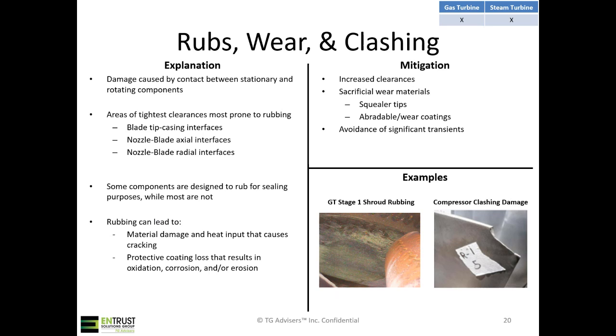The other thing that you can do is avoid significant transients. The big thing is that if your gas path is really hot, but your casing is still cold, you can cause severe rubbing. And it's kind of the same thing in the steam turbine. It's important to make sure that everything is thermally soaked and heats up together to avoid any sort of significant rubs.